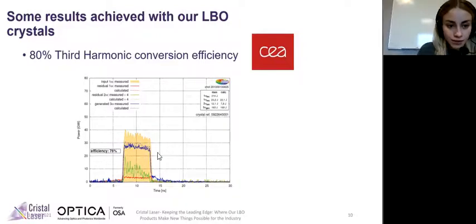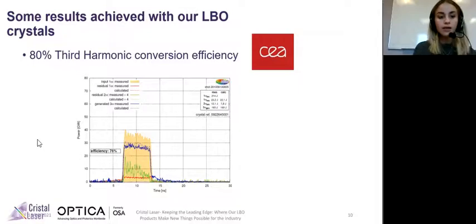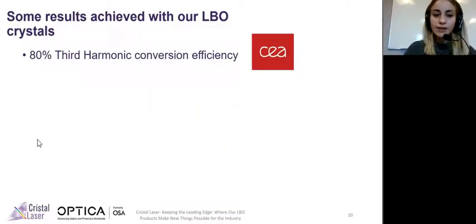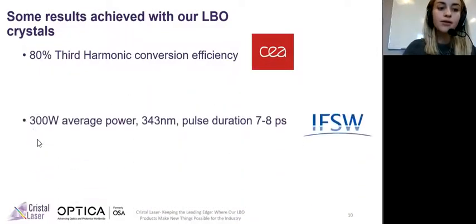You can see here that the efficiency was around 80%. To be precise, it was 76%, sorry. Then we can also talk about the 300 watt of average power reached by the IFSW, which is part of the University of Stuttgart in Germany, with a wavelength of 343 nanometers and a pulse duration of 7 to 8 picoseconds.